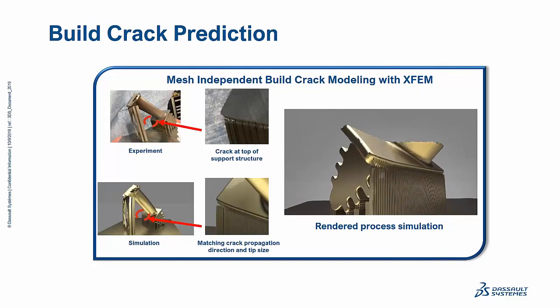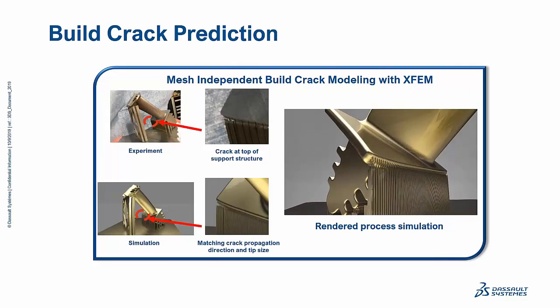Other things that are related to thermomechanical simulation are failure simulations. What you see here is a validation of an experimental effect where we have the structure, which is a turbine blade that is being printed, and as you can see in the experiment, there's a crack developing between the support structure and the actual part. The crack develops during the print process. It's not something that is interesting for us afterwards, where we simply say, oh, it's red here, something could have cracked. What we see instead is the part cracking during the print process, and that in turn affects, of course, the temperature distribution, because at this point, the support structures, which serve not only to support the part, to hold the part in place, but even for thermal management, don't really do what they're supposed to do.